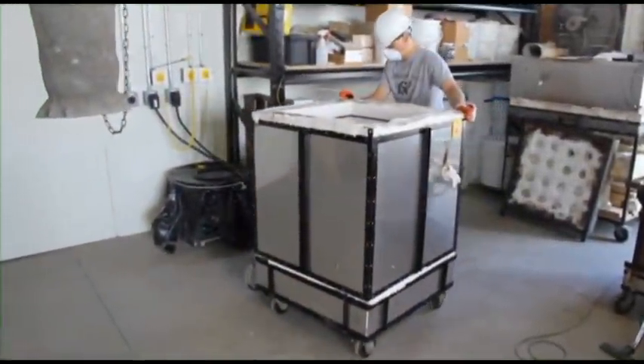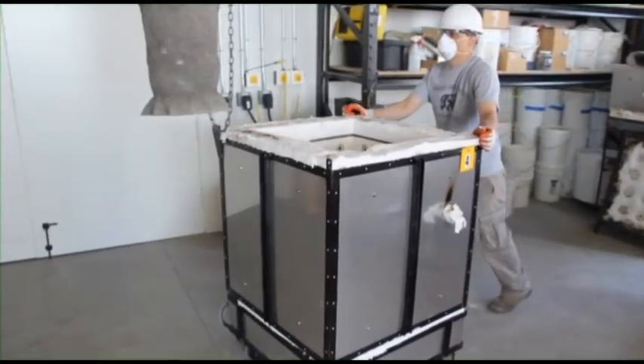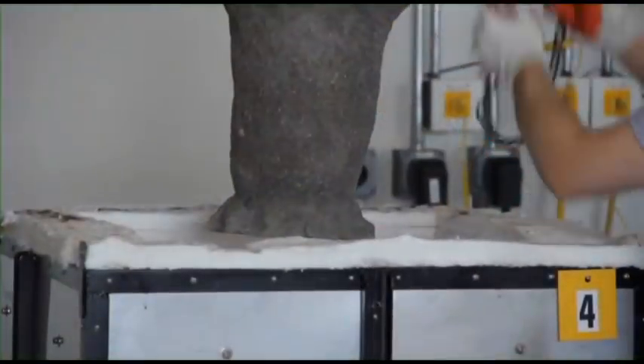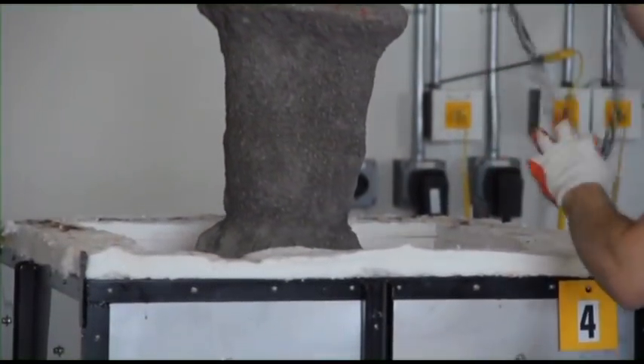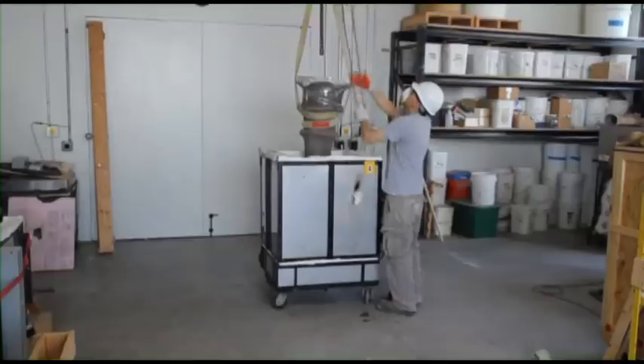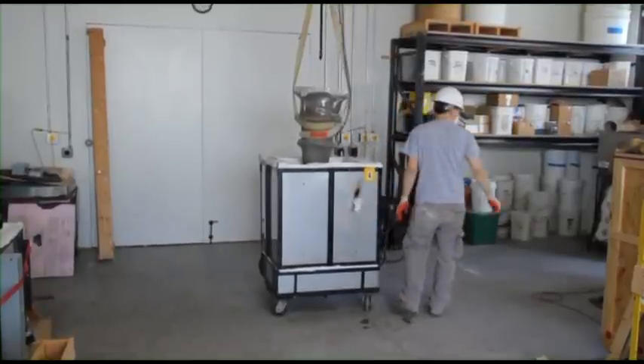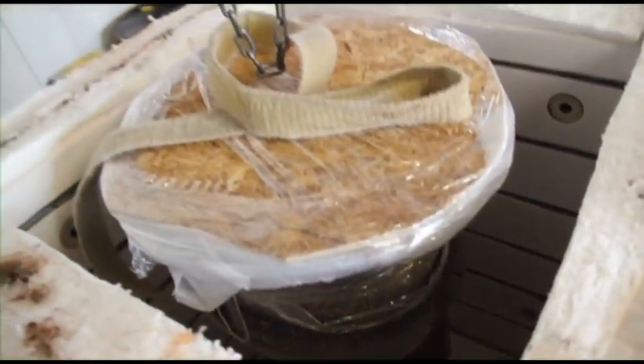So that goes into the kiln and doesn't need any support with kiln bricks around it. It just goes right into the kiln and can hold 60 pounds of glass without any worry or danger of it breaking out. And these melt for 26 hours at 1600 degrees in order to get all the big bubbles to rise up and out of the casting.